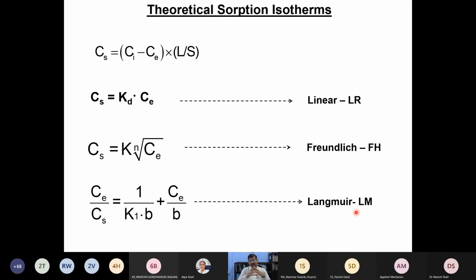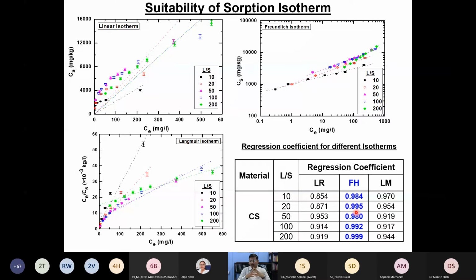The selection of isotherm depends on the nature of interaction between the contaminant and the sorbent. At the same time, it also depends on the surface characteristics of the material to a certain extent. Anyway, you need not go through that detail, but we want to assess what kind of isotherm is best suitable. One contaminant we have used in this case is, I think, a heavy metal in soil. So we try to represent it in terms of the linear isotherm, Freundlich isotherm, and Langmuir isotherm. By looking at the regression coefficient as well as the best-fit parameters, we notice that the Freundlich isotherm is good to represent the soil-contaminant interaction, since it is a soil.